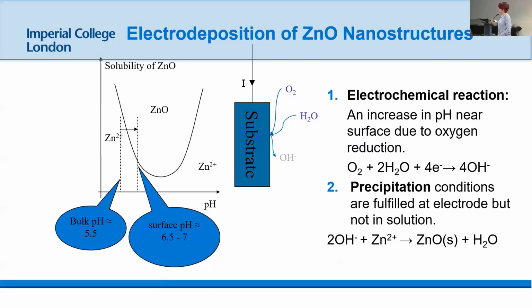And if you've got some zinc ions in a solution near a cathode, and at your cathode you are causing an increase in the pH, or an alkalization locally of that film, you're very likely to hop over into this region of the phase stability curve where we've got zinc oxide solid. All right. And so this is a process that's driven by oxygen reduction that leads to precipitation directly of crystalline zinc oxide on the surface.